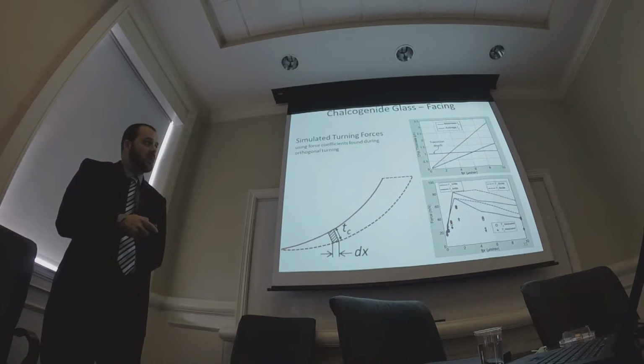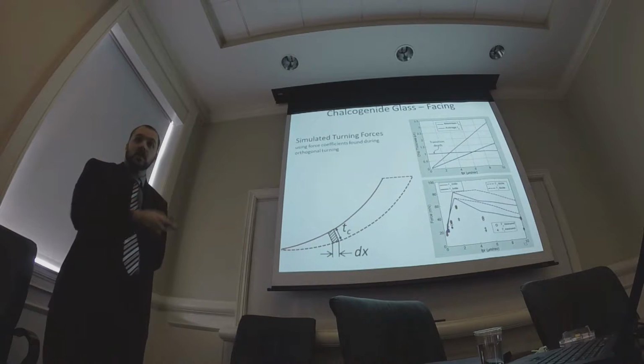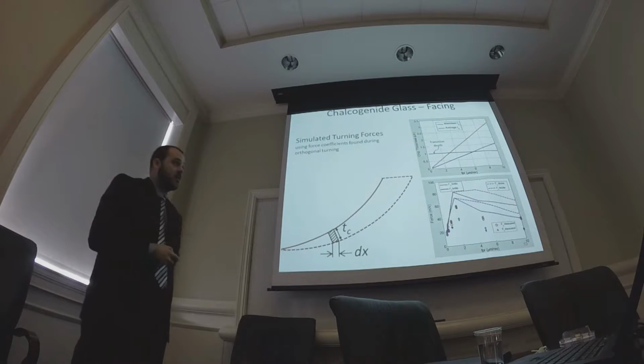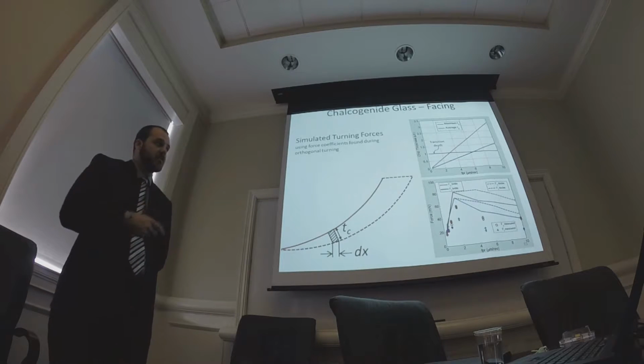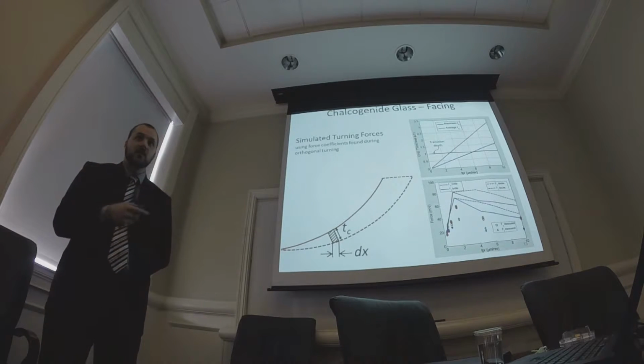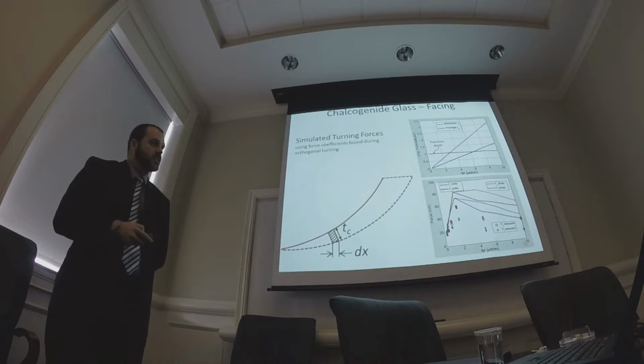So I went back and put the forces from the bottom of the hysteresis, where we're working our way from a fractured surface back towards fracture-dominated cutting to ductile-dominated cutting. And the trend better matches the forces that we're seeing.